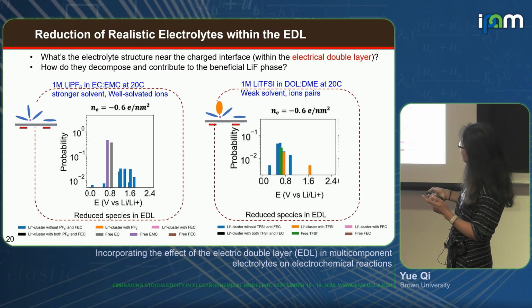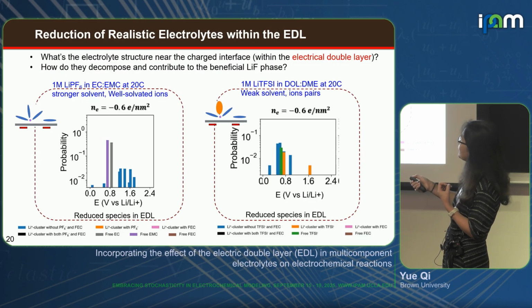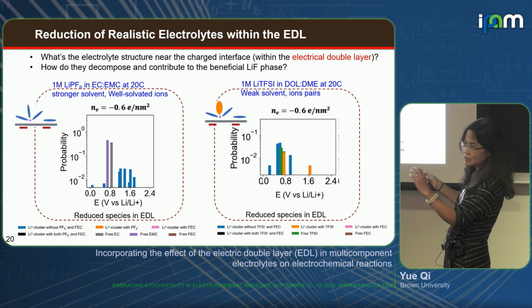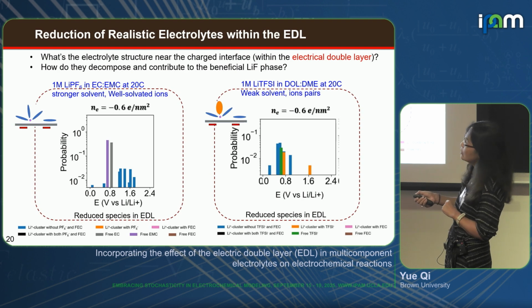In the weak solvent, because we have ion pairs, when we attract some positive lithiums, we do attract some ions to the surface, and all of the ions are lithium associated. And so that tells us you will have fluorine species near this interface layer, and in this one you don't.